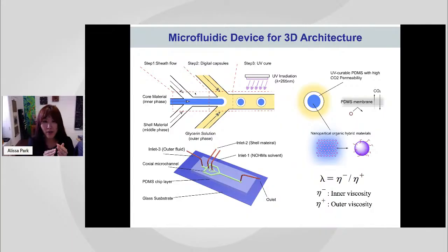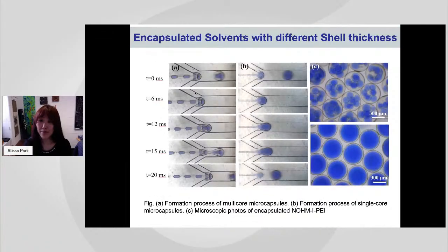And both ionic liquid and NOHMs have almost zero vapor pressure, so even if a liquid is inside, it wouldn't evaporate out of that membrane shell and stays within the capsule, these microbeads. At the same time, the porosity of this shell material has to be good enough to let CO2 in without having any diffusion limitation. So these are actual materials we made in our lab.